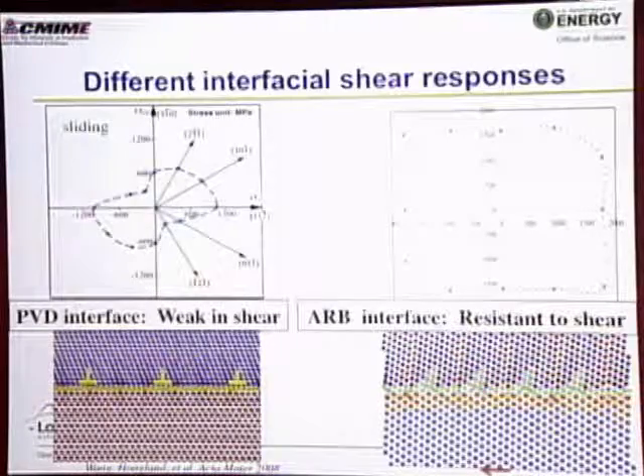And the reason for this are the different interfacial shear responses. If we think about our PVD interface, which was weak in shear, this is the one that just formed a nice sliding type of interface, it's flat. And if you were trying to move this along this deck of cards, you can move it in almost any direction, and the stresses to do that are relatively low. That's what this line here represents. So 600 MPa, 700, 600, something like that.